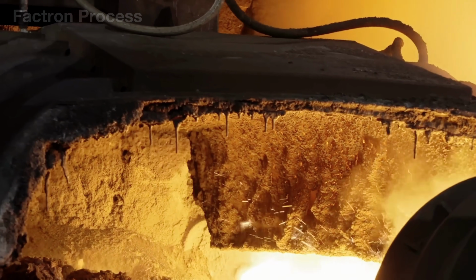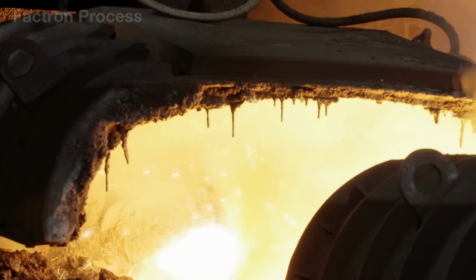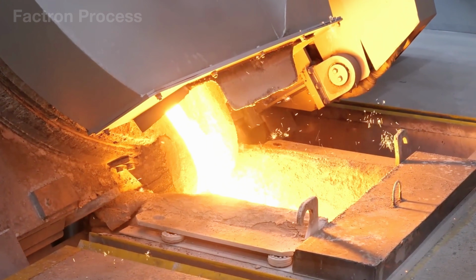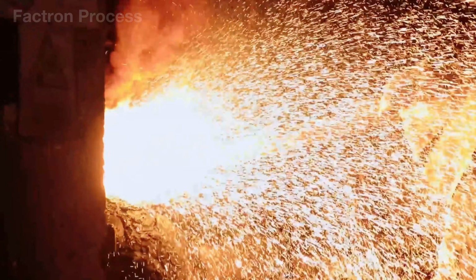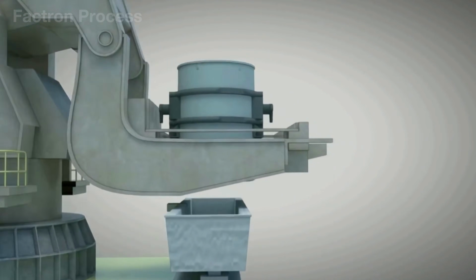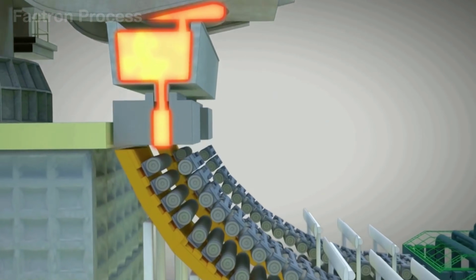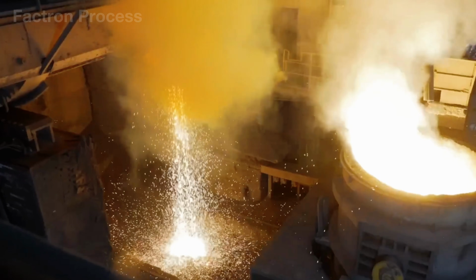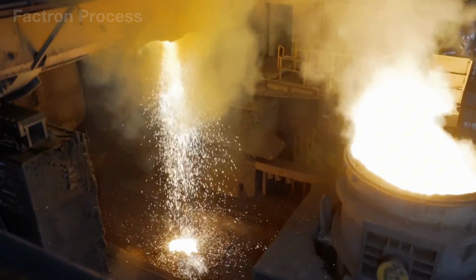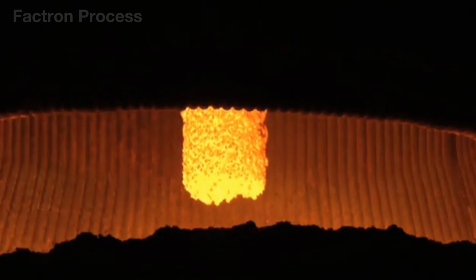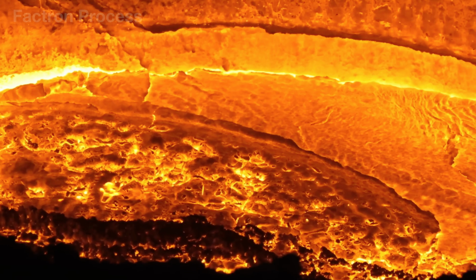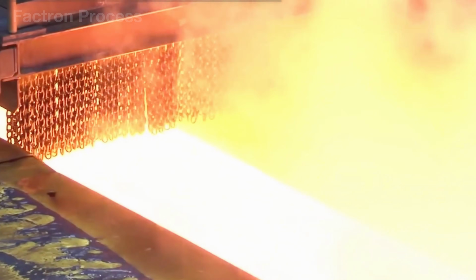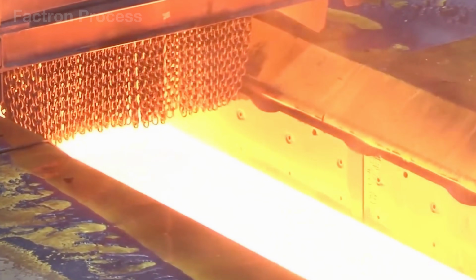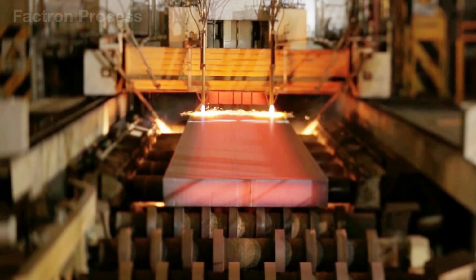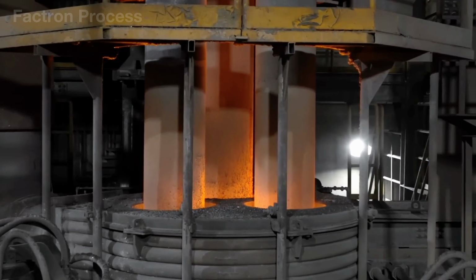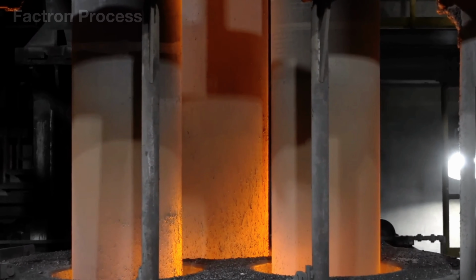After refining, the glowing molten steel is poured into a tundish to stabilize the flow before entering a multi-strand continuous casting machine, or CCM. Here, the molten steel passes through a copper mold, cooled by circulating water flowing at 12 to 15 meters per second. Its outer shell solidifies almost instantly to a thickness of several millimeters, while the core remains molten. A continuous roller system draws the strand downward and guides it into a fine, high-pressure water spray chamber, where it gradually solidifies from the outside inward.